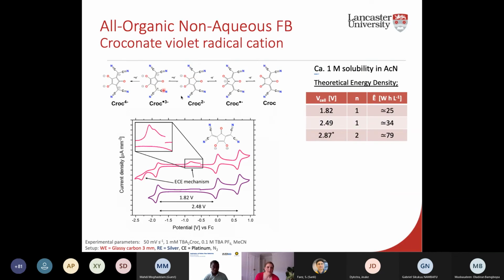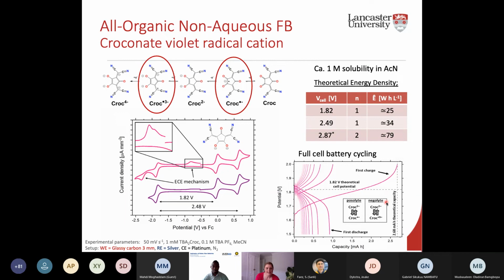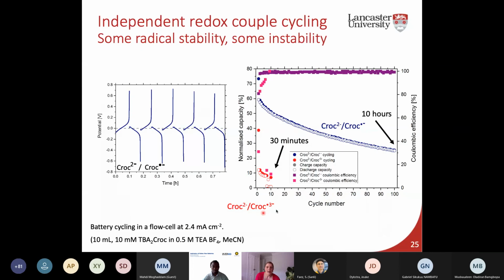Same with the croconate violet. We had this lovely voltammetry where we had a nice 1.82 volt difference between our species here, but they were going to two radical states when we were charging, and we had some nice looking energy densities that were competitive with a vanadium flow battery. But the full cell cycles completely deteriorate, and that's because the Croc•3- trianion radical is unstable when it's in its charged state compared to this other radical, which is very stable.